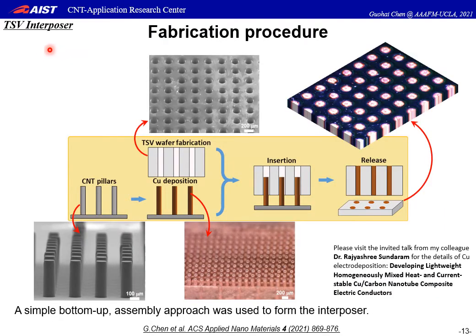The second application is the Thru-Silicon-Via interposer. Here is the fabrication procedure. We use a simple bottom-up assembly approach. First, patterned CNT pillars were synthesized, followed by homogeneously high-content copper electrodeposition. Meanwhile, a through-silicon-via wafer was prepared by conventional deep RIE process with closely matched hole sizes. Then the CNT–copper pillars were inserted into the TSV substrate to form the interposer using a 3D manipulator. Please visit the invited talk from my colleague Dr. Rajyashree Sundaram for the details of copper electrodeposition.